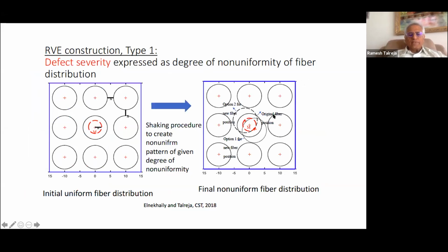So how do we go about quantifying this now? So that's where our novelty comes in. We have taken two different paths, and I'll describe both to you. I'm calling that RVE construction type 1 and type 2. In type 1, which is more common in the literature, you start out with a square window in which you place fibers in a uniform pattern with separation between surfaces constant x, that's shown there. And then you shake it. It's called the shaking method.